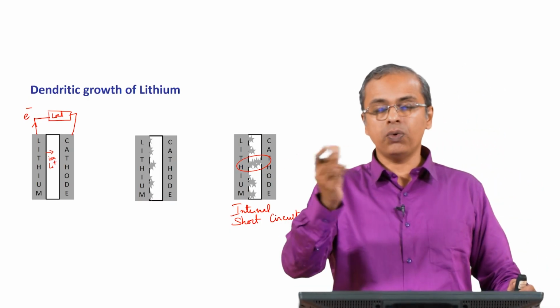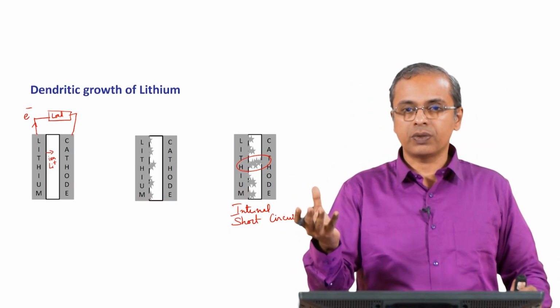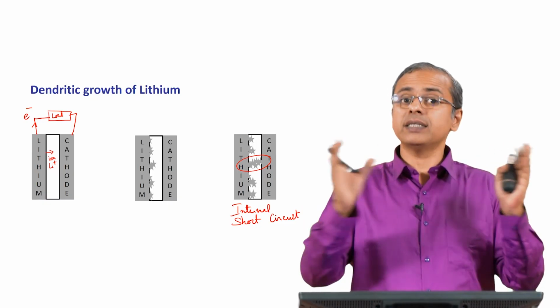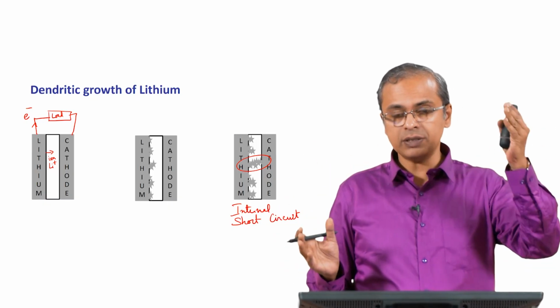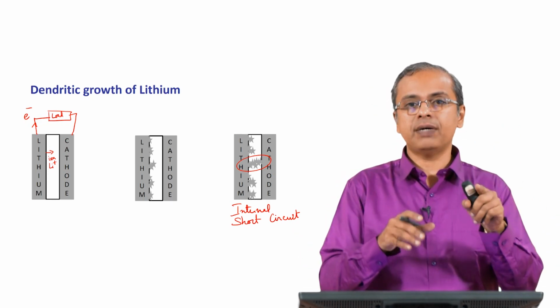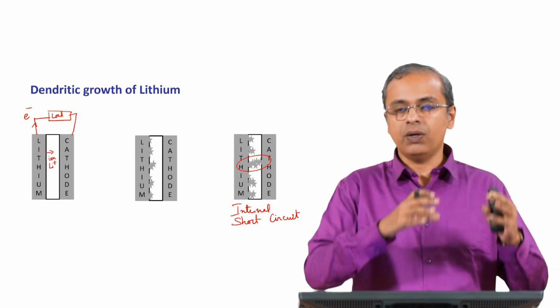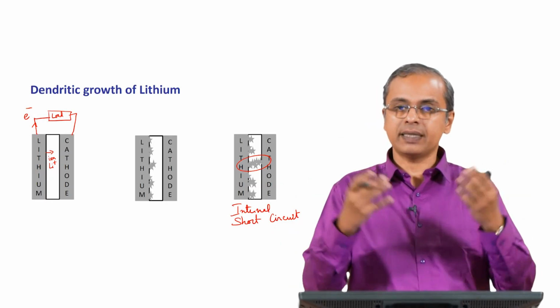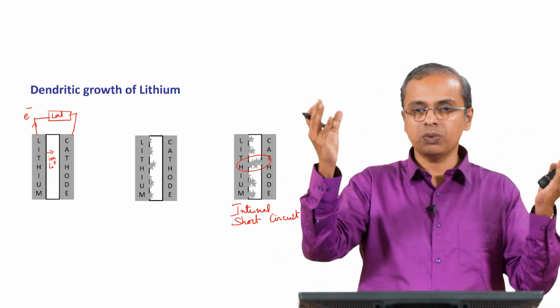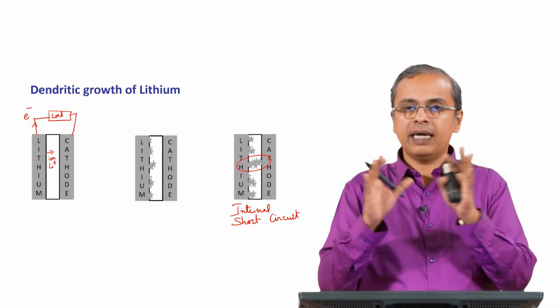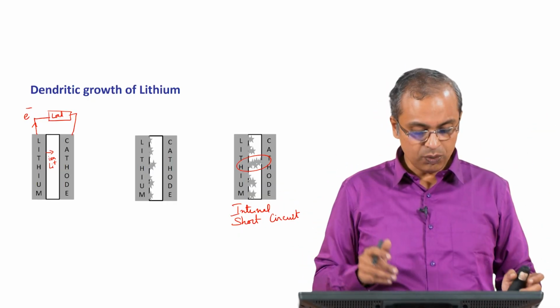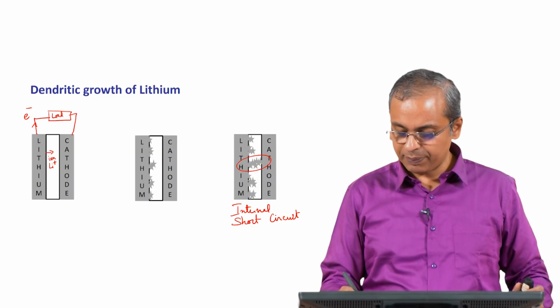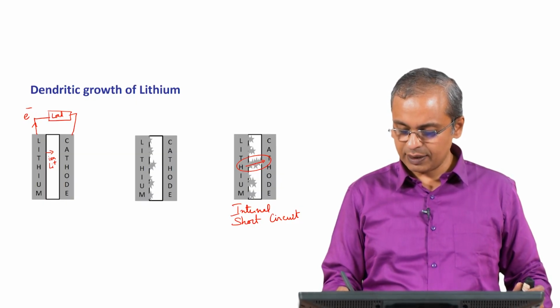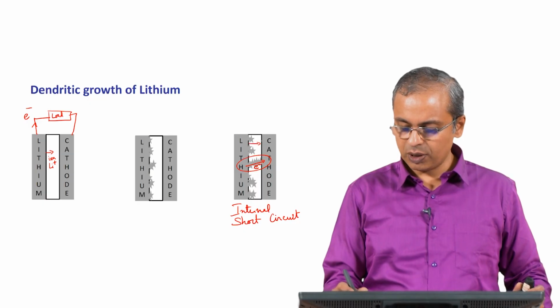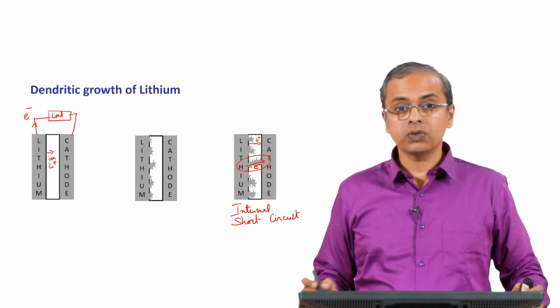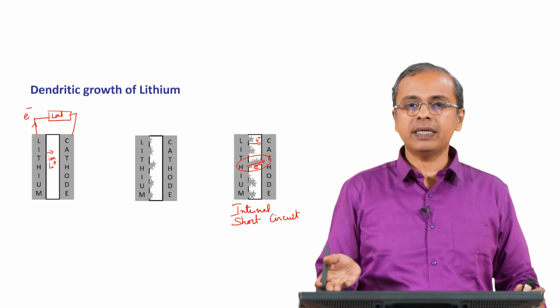Okay. So, the moment you remove the load, the battery is an open circuit. If there is no load there, this battery is an open circuit, the reaction stops, because the electron also has to flow, the ion also has to flow. Both those steps have to happen for charge neutrality to be maintained. Only then the circuit is complete, the reactions are complete, and the reactions will take place. If you open up the circuit outside, there is no path for the electron to go, everything stops, right. So, now when you have an internal short circuit, both of them can happen. You can have electrons just go across like that, and you can have ions that do go across like this. So, you no longer need an external circuit, everything is happening inside the cell.